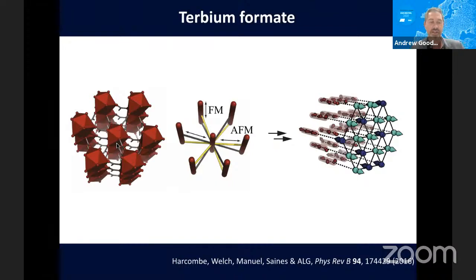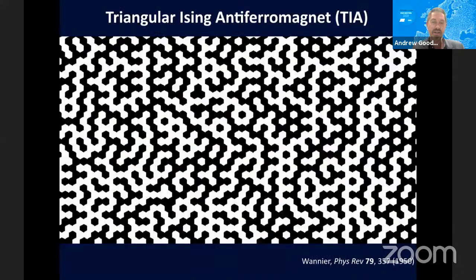But of course, as you might have guessed, the interactions from one column to the neighbor are antiferromagnetic, and this gives rise to this same sort of geometric frustration we saw in those trisamide crystals. And again, the sort of states you access are conceptually related. In this case, this is a material that has some very good magnetocaloric behavior, and the behavior of this particular system is key to that. This is what